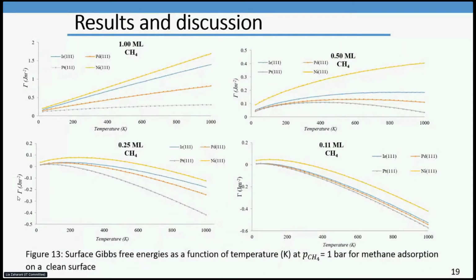This figure shows the surface Gibbs free energy as a function of temperature at a pressure of 1 bar for the methane adsorption on the clean metal surface. We observe that at coverage of 0.5 and 1.0, the surface Gibbs energy is positive, and at coverage of 0.25 and 0.11, the Gibbs energy is negative. And the more negative this Gibbs free energy, the more stable the adsorbed structure. And you can observe that platinum has the most stable structure, followed by palladium, followed by iridium, followed by nickel.